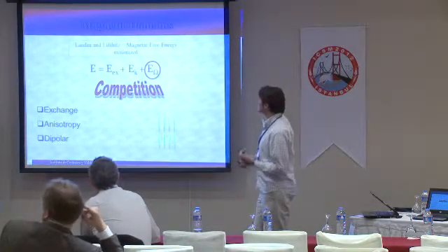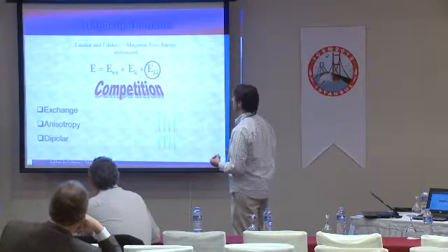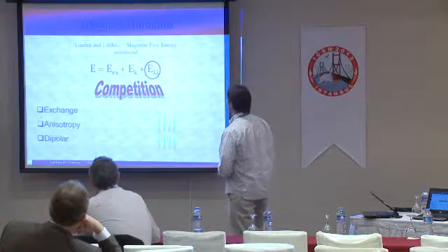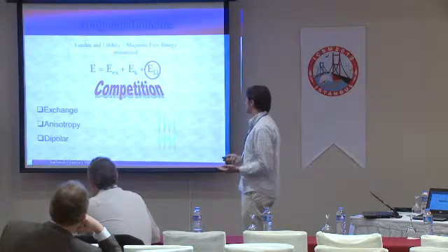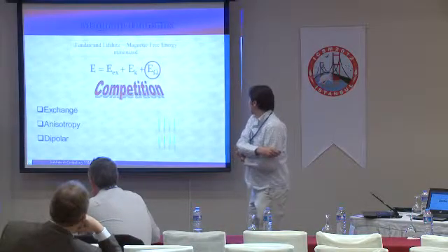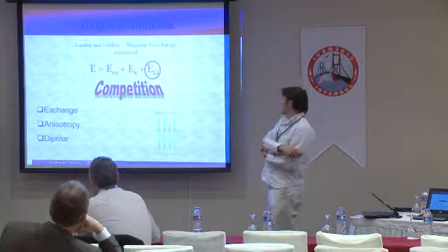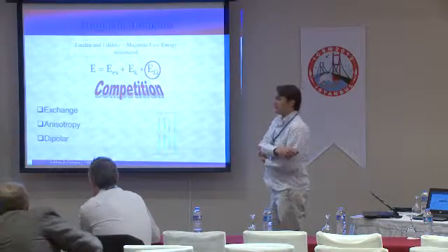But then maybe one could say that the term more responsible for the appearance of magnetic domains is this third term, the dipolar term, because in this picture here, one would get just a single domain magnetic system. But this third term, the dipolar term, wants to avoid the formation or the accumulation of magnetic poles, and that's why it's going to promote the formation of domains.